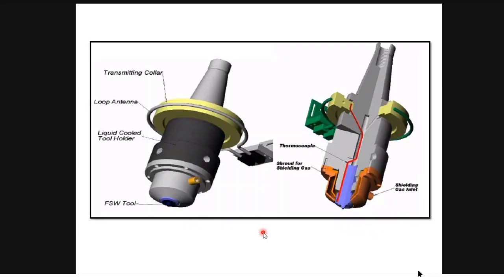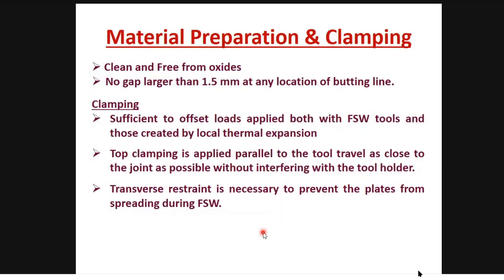And there are many methods, many provisions. This is the cut section inside, showing how the cooling water circulates through the circuit and other things. Even Mr. Venkatesh showed these developments that took place in the tool. All right, so there are many preparations required. You have to clean and free the surface from oxide, with no gap larger than 1.5 mm at any butting line. The clamping should be perfect, because a lot of forces will be acting. It's not like the clamping for aluminum alloys and magnesium alloys. Here you require perfect clamping of the base material.